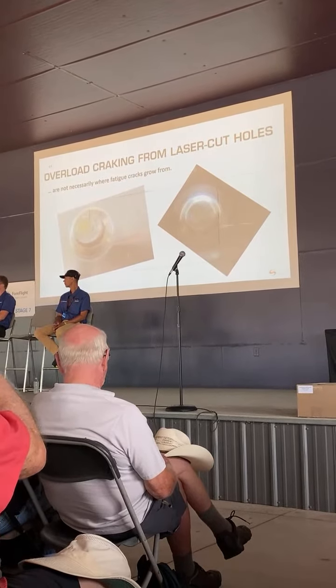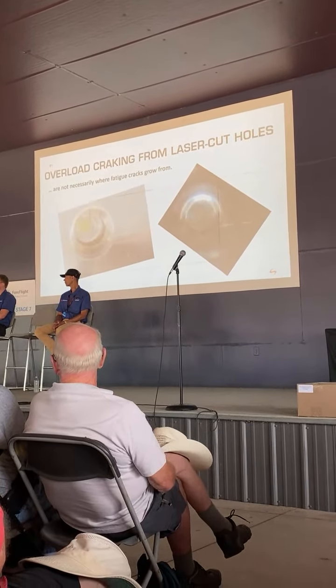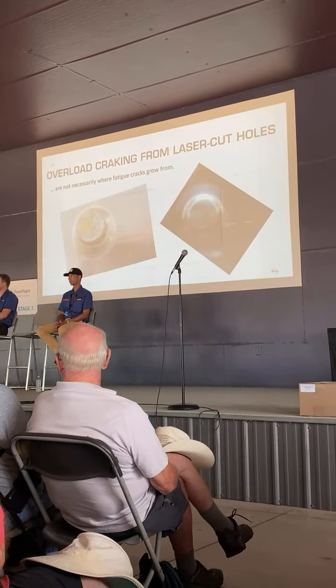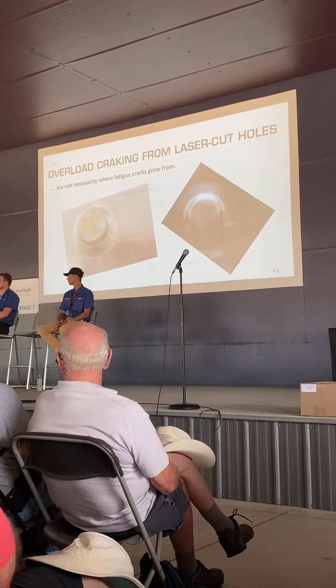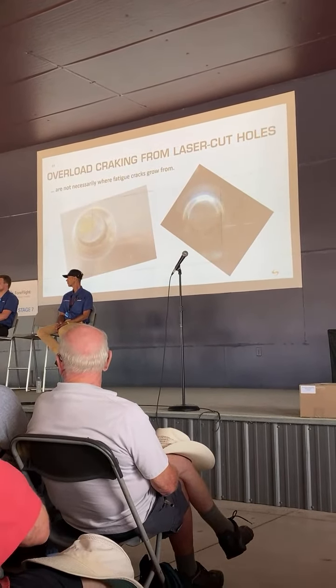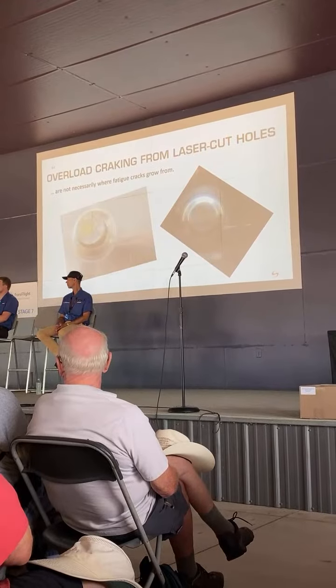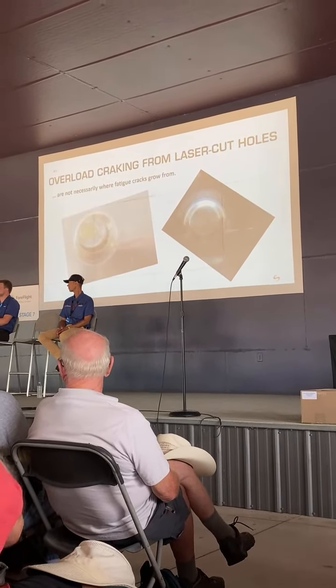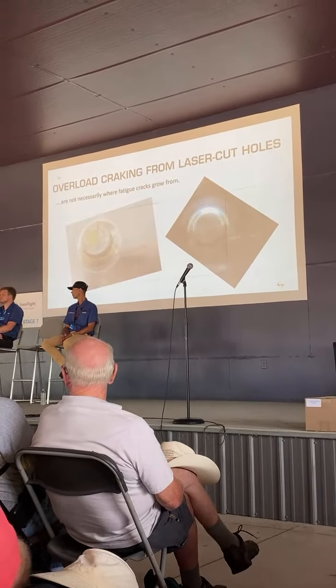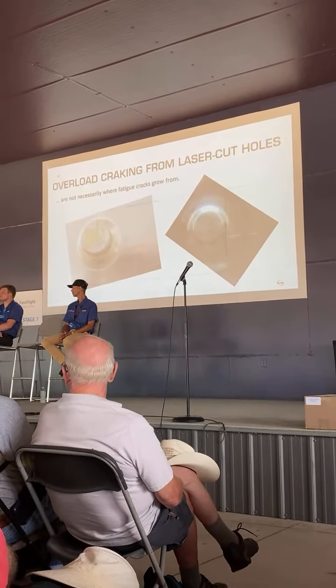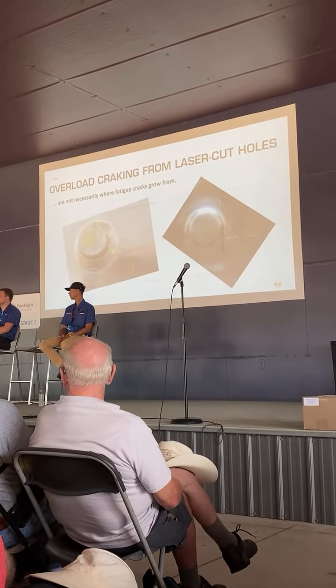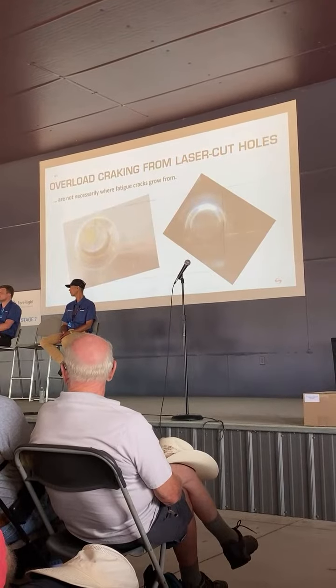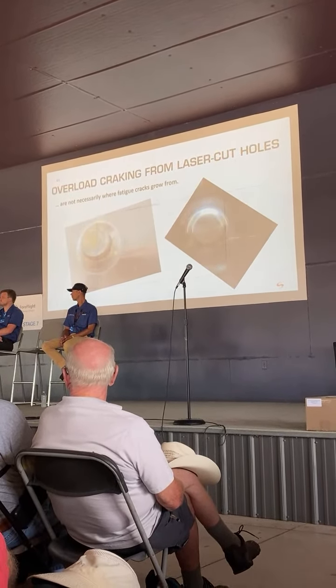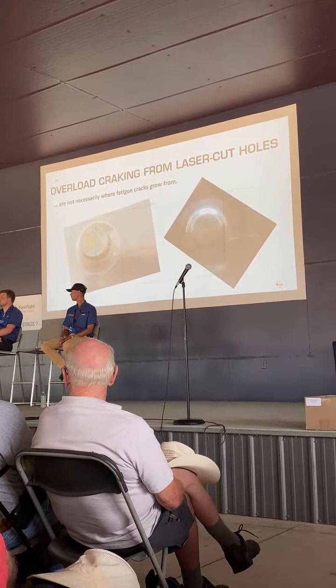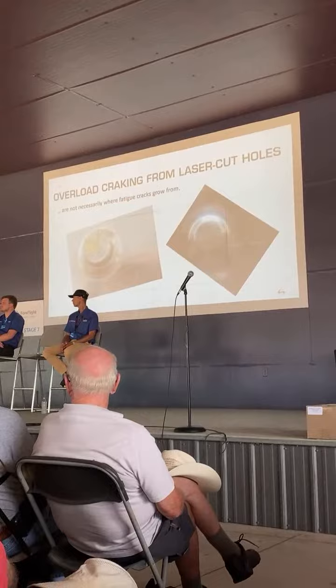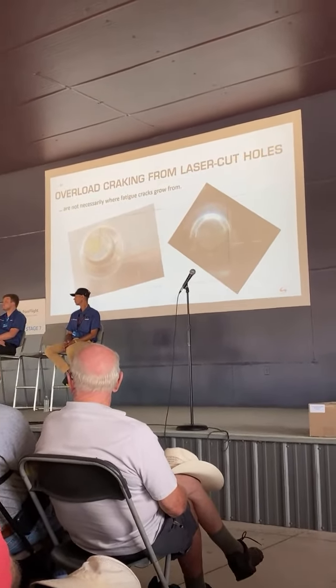A case that happened in the real world that we're all familiar with is the Comet, the de Havilland Comet. They pressurized that airplane to 2.5 atmospheres, then relieved it. And when they did that, they introduced cracks into the structure that then opened up and closed up and left that residual stress at the crack. And then they ended up testing at 1 atmosphere for 16,000 cycles of equivalent flights. And the problem was the cracks that formed, that eventually fatigued their test specimen, formed in other areas than where those initial cracks were formed.